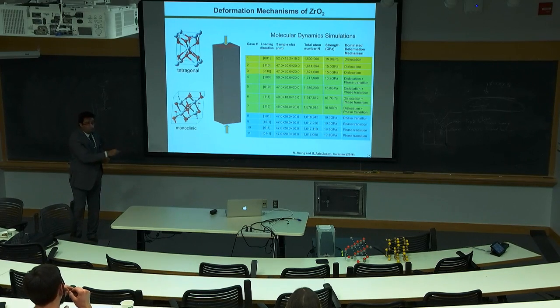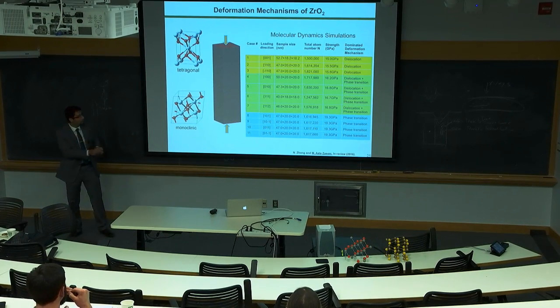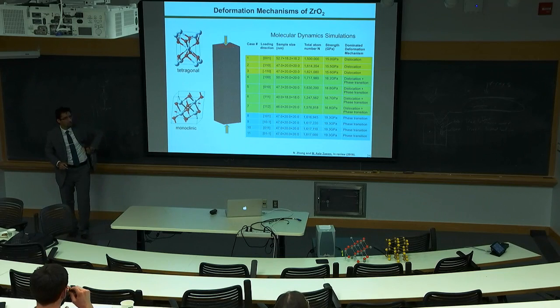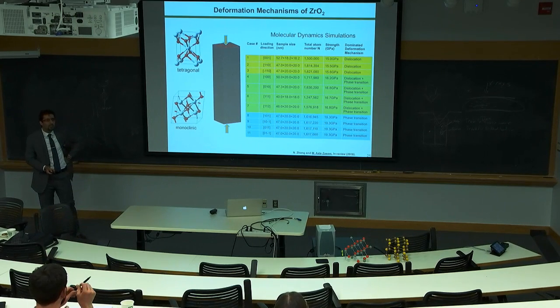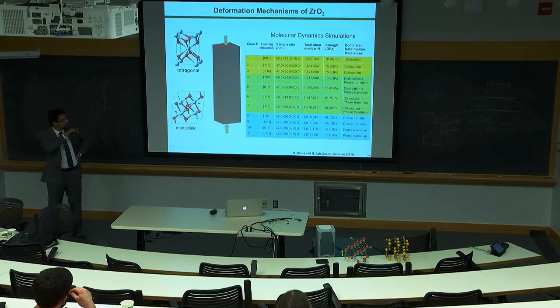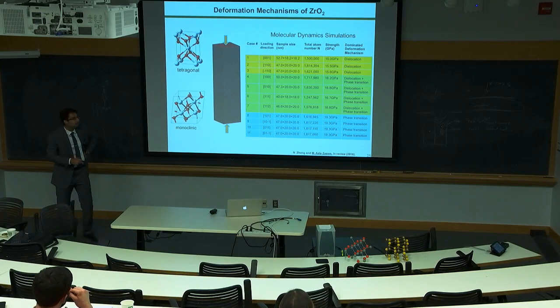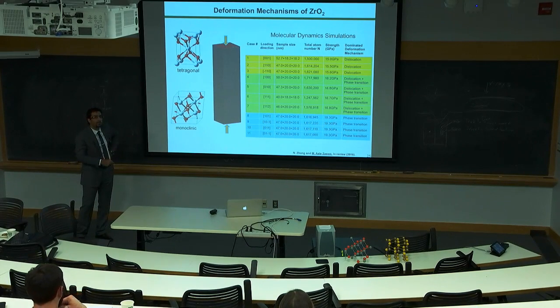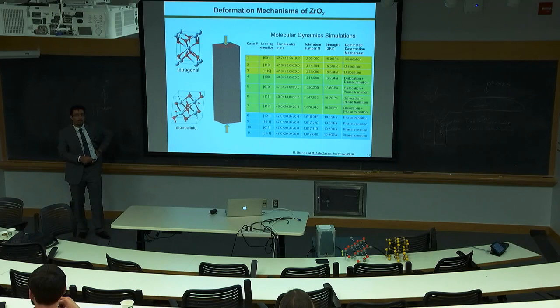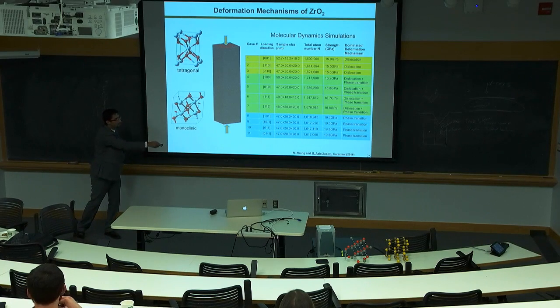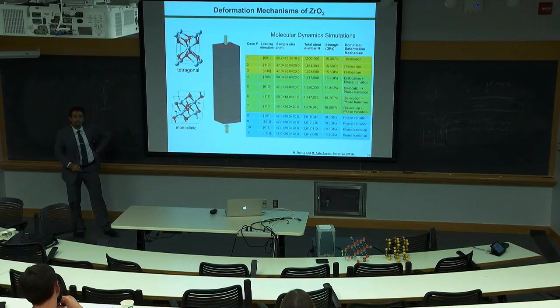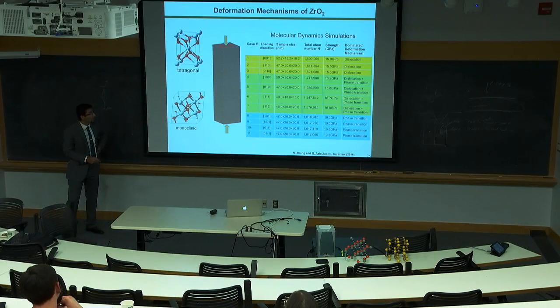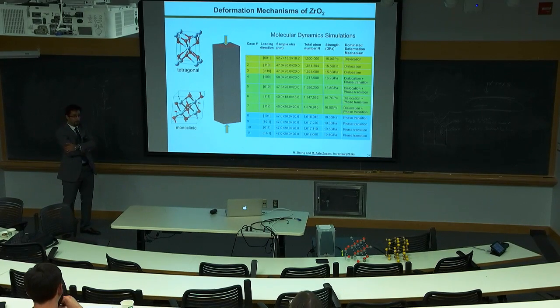The next four, dislocation and phase transformation, and the last one, phase transition. So we found a regime that changes the deformation mechanism, going from dislocation to complete phase transformation. And the reason was the direction of loading. Basically, it's an orientation-dependent problem we are looking at.